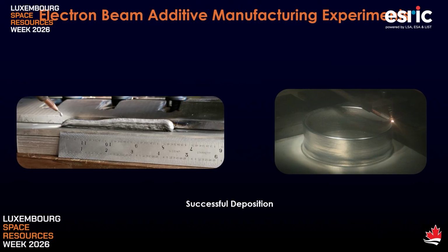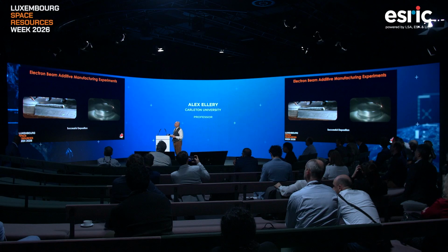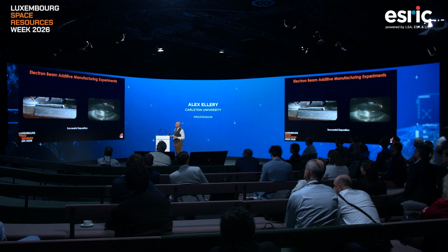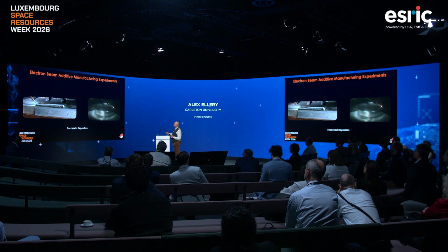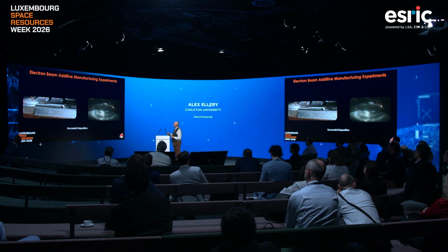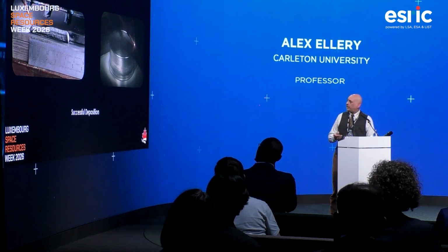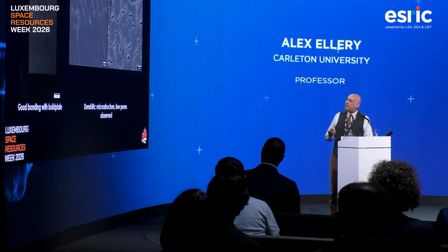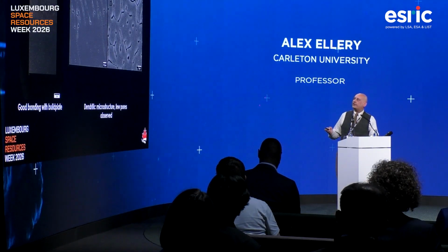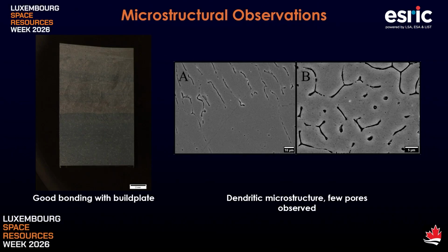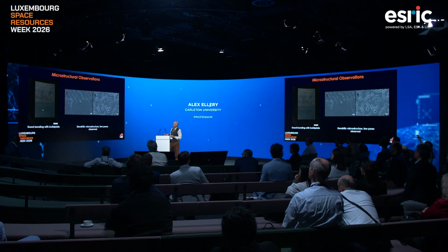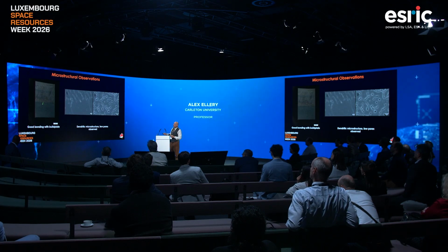So this is the first result. We call it the turd because it doesn't look very pretty. But this is what we use for slicing. We slice through this to get a cross section of it. And here is the same metal being used to build a kind of plate, and I'll show you that in a minute. This is the microstructure. When we took a section through that turd, this is the upper part, what we deposited in layers, and this is a section through the build plate. And as you can see, there was good bonding between the two.